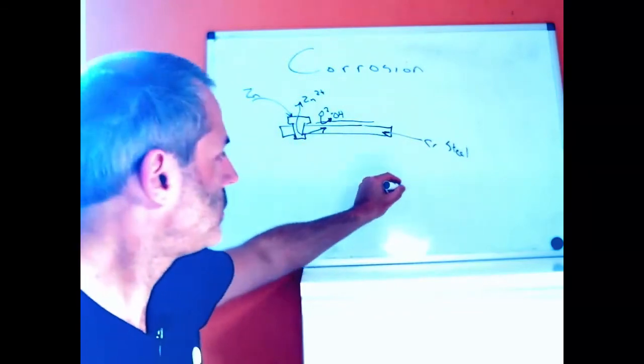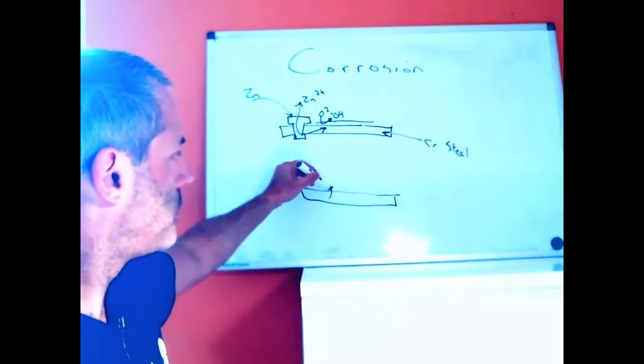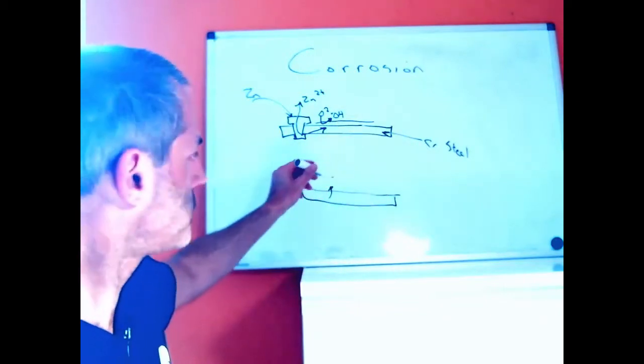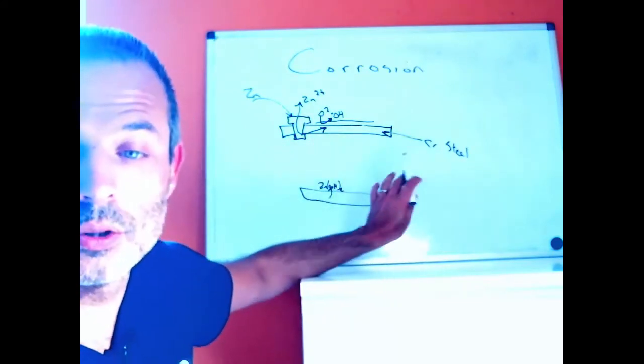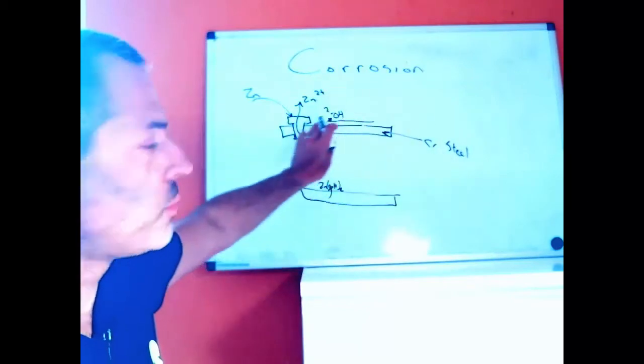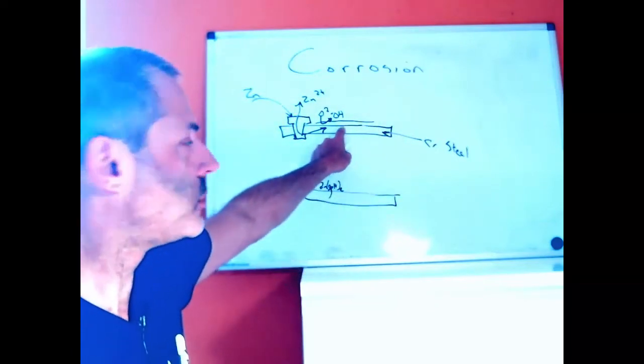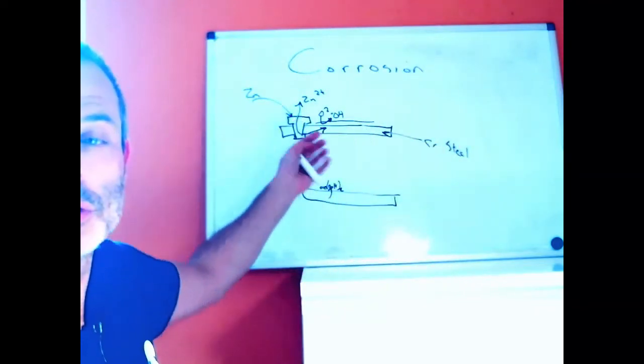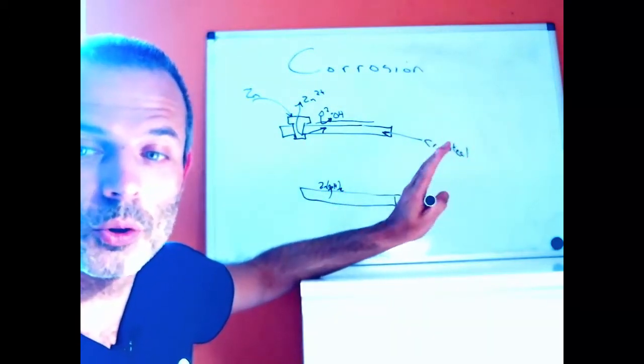Normally if we had a piece of zinc corroding, as the zinc dissolves it gets into a solution containing hydroxide ions created from the other part of the reaction, and that forms zinc hydroxide at the surface, which is a solid and blocks further reaction. But if we separate the two reactions, the zinc part becomes slightly acidic and the hydroxide part becomes slightly basic, and if they're not close to each other the zinc dissolution is comparatively unhindered.